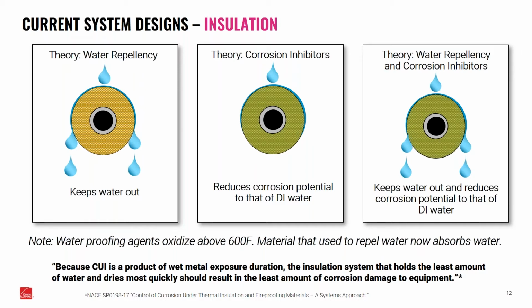The only challenge with that is that even though you have all that water there and that corrosion inhibitor to help mitigate that corrosion part of that, you still have that impact of the lower thermal performance because the insulation is just going to conduct a lot more heat through that wet segment. And then finally, we have our third theory, which is a combination of both, where you have water repellency and corrosion inhibitors. And that seems to make a lot of sense too. And some material types actually do this, where you keep that water out and you also reduce the corrosion potential if you have any water that gets in.